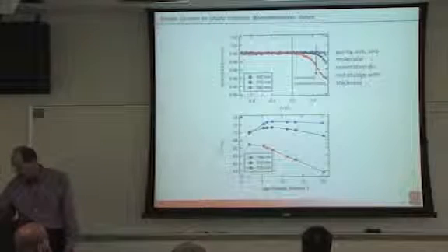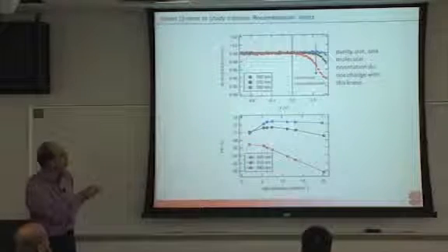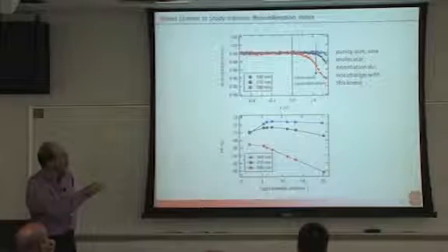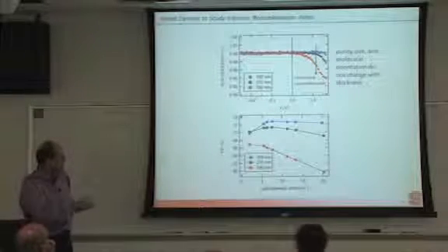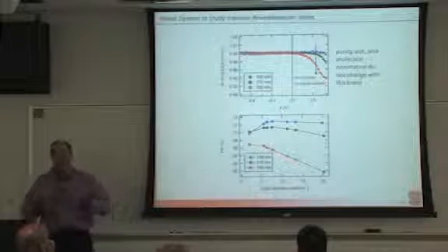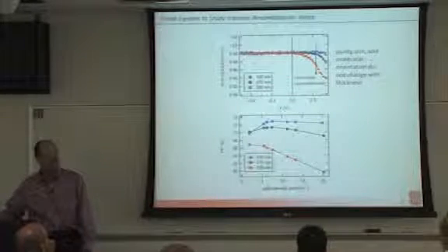So this seems to indicate that this is a nice system to study the intrinsic bimolecular recombination rate. This is again the scaling exponent that tells you what the bimolecular recombination is as a function of thickness. Here's the light intensity fill factor measurements. So we now have a tool to look at this, and maybe this allows some real careful modeling as to what is happening in the system.